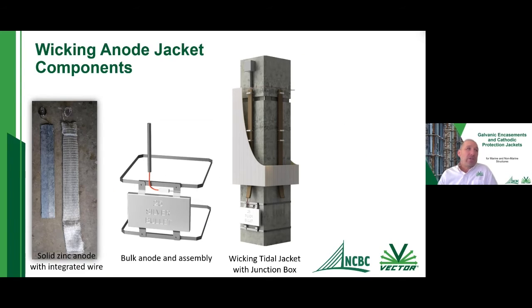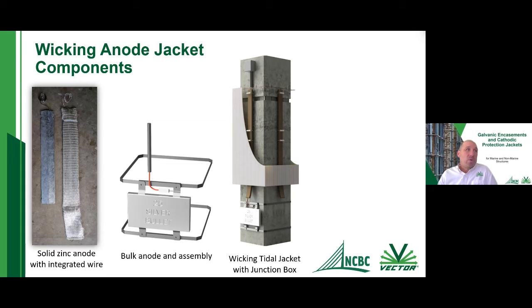And here are just some of the components for it. So on the left side, you can see the solid zinc bar. It just has a tie wire that's cast inside of it, and then it's placed in wicking fabric, and that is what's placed around the pile. And then in the middle here, we have our bulk anode. There's just a typical bulk anode assembly. This one here is showing the aluminum anodes now instead of the zinc anodes as well.